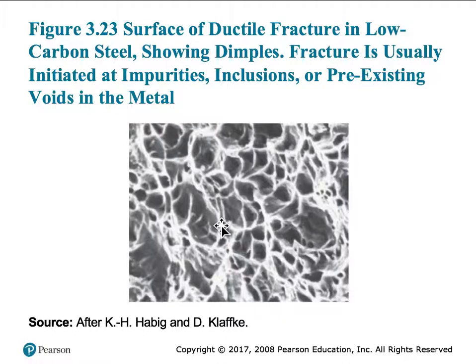in the case of low carbon steel, if you look at the fracture surface itself, you will see that there are a lot of dimples, and these dimples are formed during the failure process itself, and they will all start to link up, and as the material starts detaching from one side to the other, then the sample is held together only at the edges of these dimples, and they no longer can take the load, and beyond a certain limit those dimples will start detaching and start failing. And the fracture is usually initiated at impurities or inclusions or pre-existing voids. But sometimes you will also find that there were no pre-existing voids or impurities, but they will still fail in this manner, if it is a ductile material.